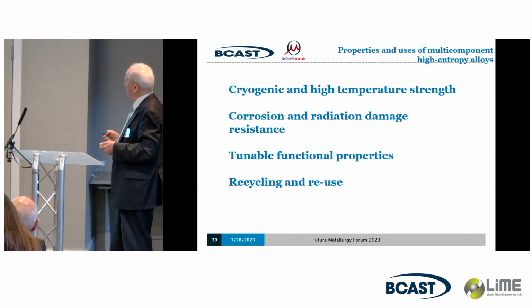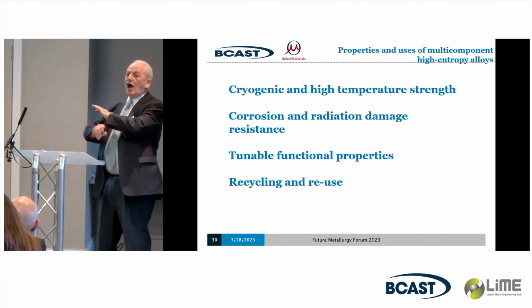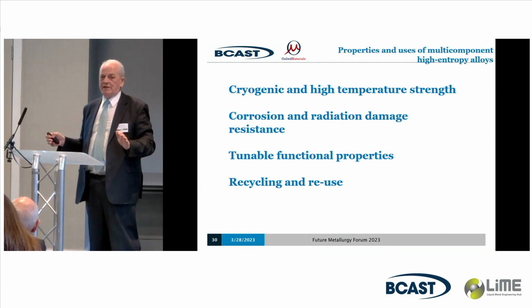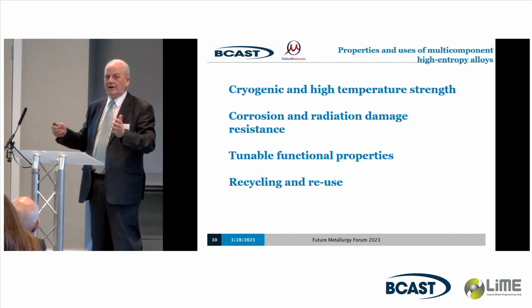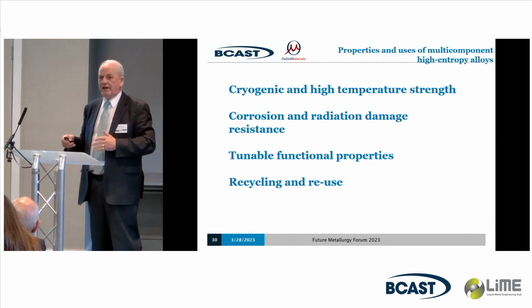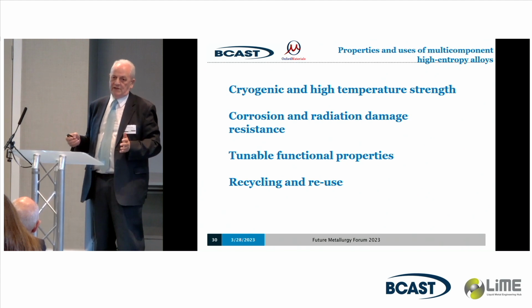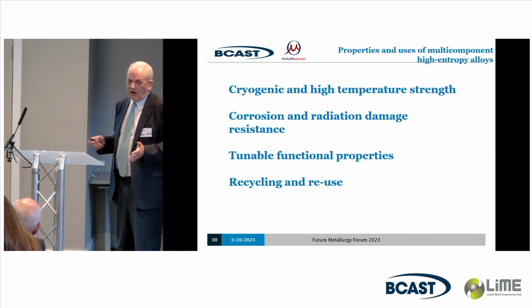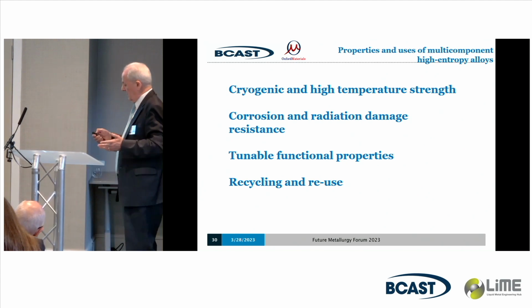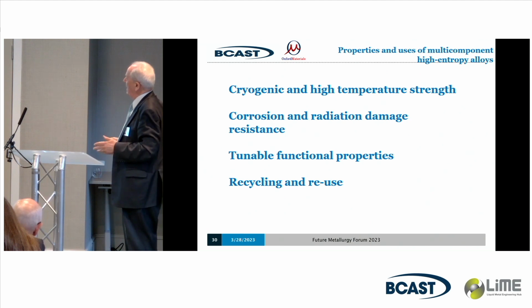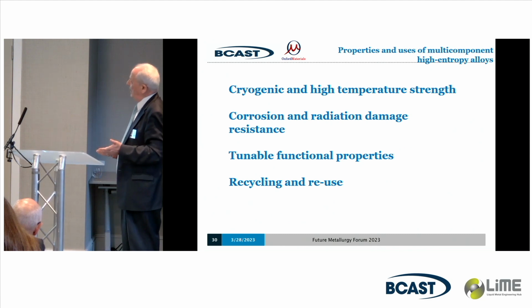The high-entropy alloys turn out to have absolutely outstanding high temperature strength. There's been almost no optimization of these materials. People are now trying to do all the microstructural manipulation, composition changes, all that has hardly been touched. So there's a way to go yet on improving these materials, so let's wait and see where we get to. They've got excellent corrosion and radiation damage resistance, better than stainless steels. You can tune the properties very often by changing the composition.